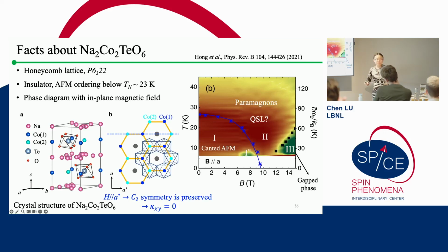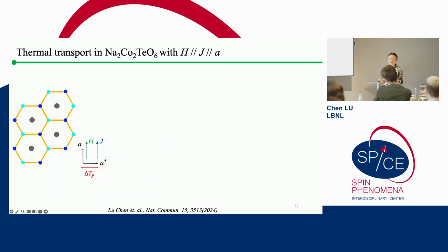So in principle, you should see a zero planar thermal Hall effect because it's not allowed by symmetry. So now let me show you guys what we actually got in our result. What we try to do here is measure a planar thermal Hall effect with both the field and the current along the zigzag direction of the honeycomb plane.